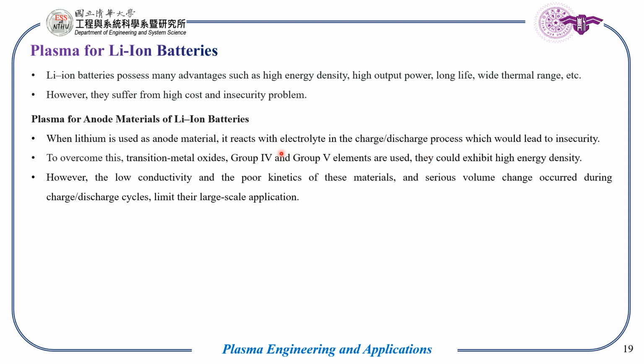So mostly transition metal oxides, like group 4 or group 5 valence metals, are used in these areas, because they have a high energy density. However, the low conductivity of these group 4 and group 5 elements and the poor kinetics of these materials cause serious volume change during the charge/discharge cycle. That is, the battery gets swollen up due to their low conductivity and poor kinetics.